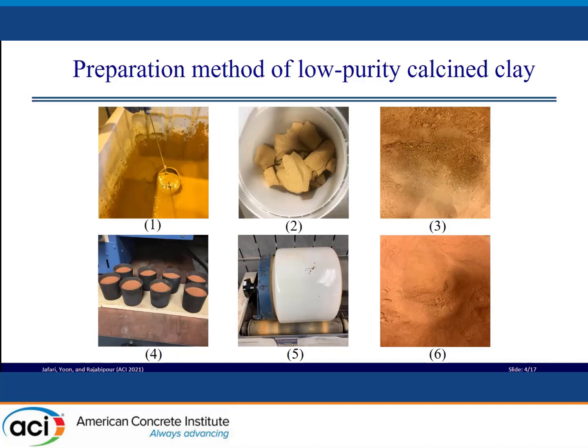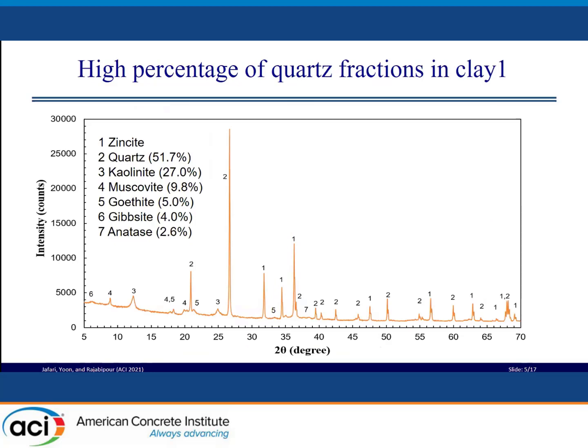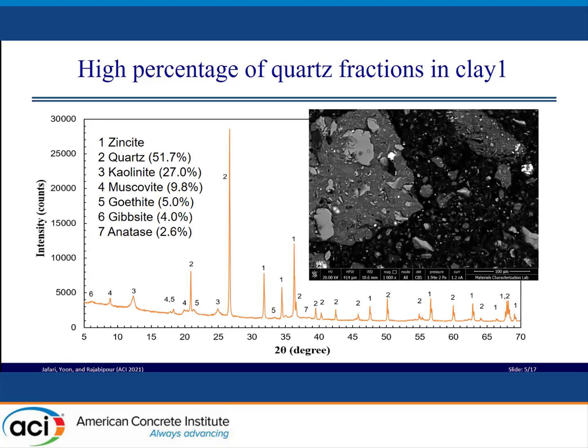The two clay samples were dried and crushed to fine particles and then calcined. The resulting calcined clays were milled in a ceramic ball mill to obtain materials with pozzolanic reactivity. The QXRD diffraction pattern for clay number one showed a high amount of quartz fraction in the clay, which also remains after calcination and acts as an inert filler. So separation of quartz is of prime importance to improve the reactivity of calcined clay. As can be seen in the SEM image, the quartz is intimately intermixed with clay, so simple density separation techniques would not be able to separate quartz from clay.